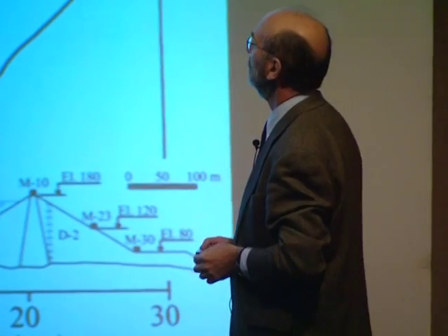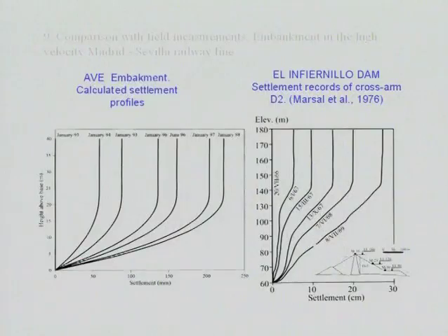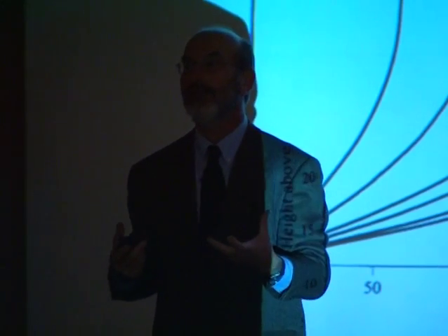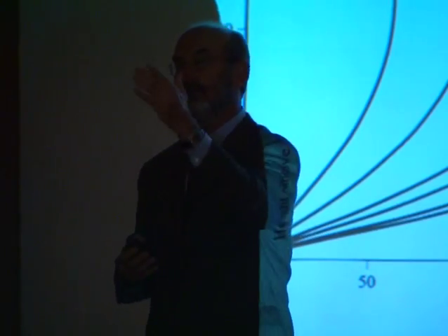the rock. Exactly, yeah, for one-dimensional conditions. For one-dimensional conditions, you see that nothing happens down to here. So for stresses below those 35 meters, you don't have any effect of water action, no deformation. That means for a good embankment, the larger the sigma y over the unit weight is, the better. If your material is strong, in the sense that this threshold value is high, as is probably the case in a quartzite or in a basalt, then it won't deform too much. This is what it's saying.